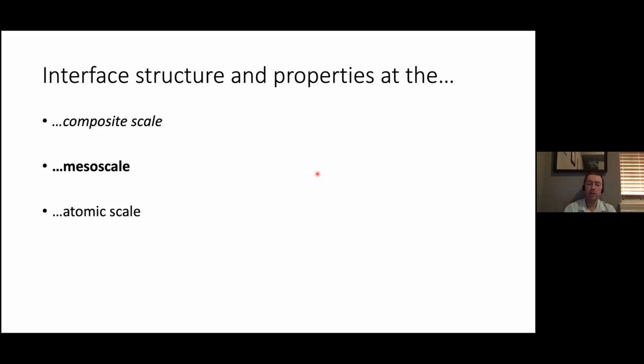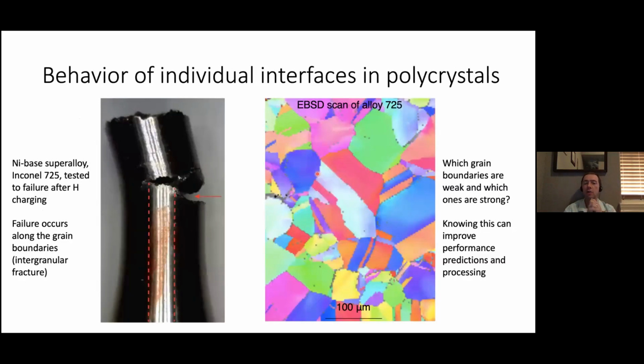And at this mesoscale, we are interested not only in the overall structure of the composite, but also how the individual boundaries in that composite behave. So in this particular vignette, just to illustrate how we do investigations on mesoscale properties, I'm going to describe a study that we did on a nickel-based superalloy. This one is Inconel 725. This sample you're looking at here on the left is about, I apologize for the missing scale bar, about 1 centimeter in diameter. And it was tested to failure in tension after charging with hydrogen.